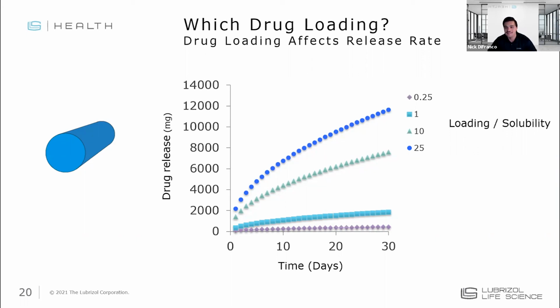We can get into a conversation on solubility of drugs and polymers, but just to simplify the conversation for today, let's just take a look at these two different loading levels. One, shown with the blue squares on the slide, is drug loading at the solubility limit of the polymer, and the blue circles are 25 times that loading. And the takeaway here is you see there's 25 times the loading, but the results that we see in vitro for drug release are not 25 times higher. It's not a linear relationship. The release rate doesn't scale linearly with drug loading. So this is something that we can change to affect drug release, but the impact is going to vary depending on how the drug and polymer are interacting.